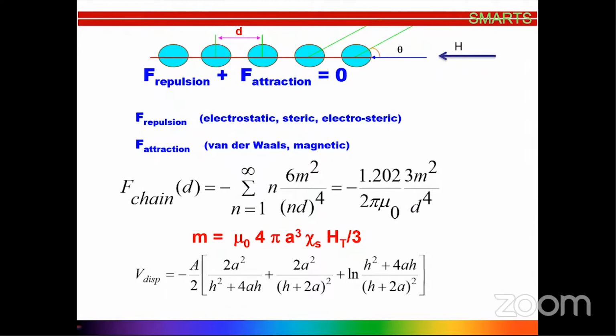And the long range attractive interaction which you can control is the magnetic interaction, which you can compute for infinitely long chains using this expression. And the magnetic moment is a function of the applied magnetic field. That also you have the information, and you can compute the van der Waals interaction. By using these equations, you will be able to get the net interaction forces.